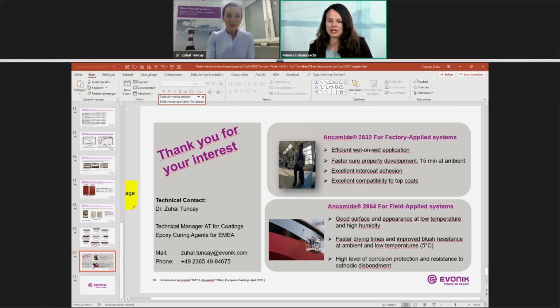With which corrosion inhibitors used in the system do they reach 10 for scribe creep blister after salt spray test after 1000 hours? Yeah. Zinc phosphate pigments we used here. Okay.